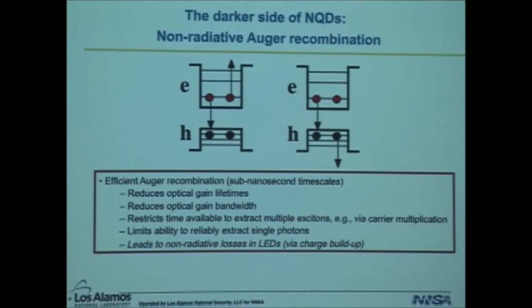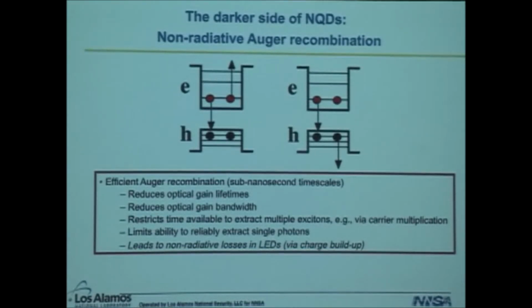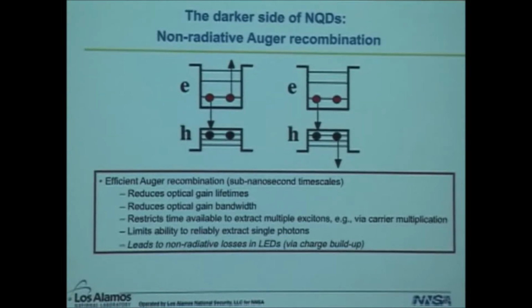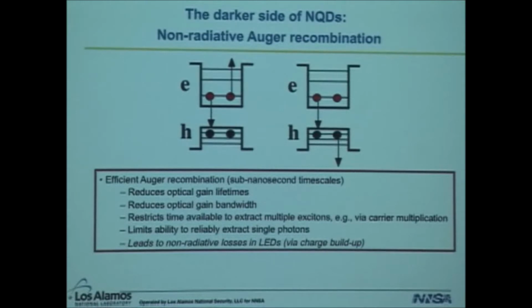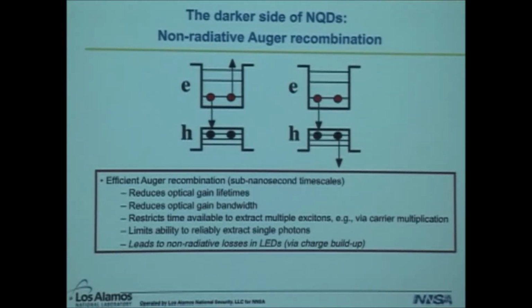with respect to many potential applications, and I list some of these here. In terms of using quantum dots for lasing, when you have efficient Auger happening, you reduce your optical gain lifetimes, you reduce your optical gain bandwidth. In the case of photovoltaics and energy harvesting applications, you restrict the time that you have available to extract multiple excitons because they're being consumed by the Auger process. And in addition, if you want to generate single photons, it's hard to reliably extract single photons when Auger is active. And lastly, in the case of light-emitting diodes, for example, for solid-state lighting applications, in a standard electrically pumped or driven light-emitting diode, the light-emitting material can easily become charged. Extra charges can build up, either electron or hole carriers. And so in that case, Auger will really diminish the efficiencies that you can obtain from your light-emitting device if the active emitter is a quantum dot.